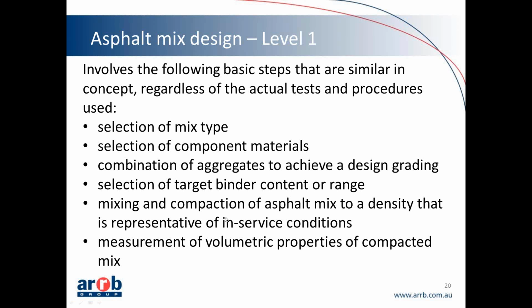Once the selection of the asphalt type has been made, this mix design procedure starts really with level 1 testing, which is again the determination of the volumetric properties. That includes testing of the bulk density, maximum density, the air voids, the voids in the mineral aggregate, the voids filled with binder, and if required the binder film index.